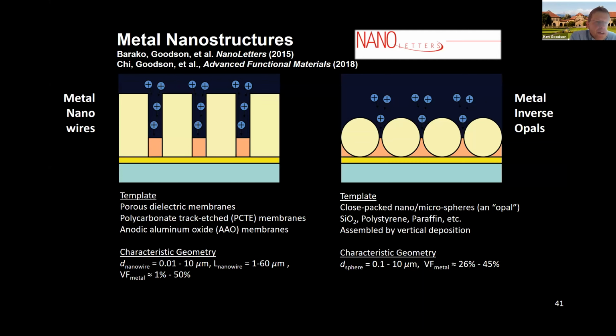But there's actually an opportunity to take some of these fabrication techniques and apply them in the area of heat transfer. Traditionally, metal structures for heat pipes and other devices have been made using sintering of balls or wires or other types of structures, and they're relatively crude in their geometric precision. If you start with a nanowire based on a polystyrene or other type of structure, or if you start with an array of beads of polystyrene, and you can get them in a close packed structure with dimensions down to 10 microns or even less, you can then electroplate around that structure and generate a highly systematic porous